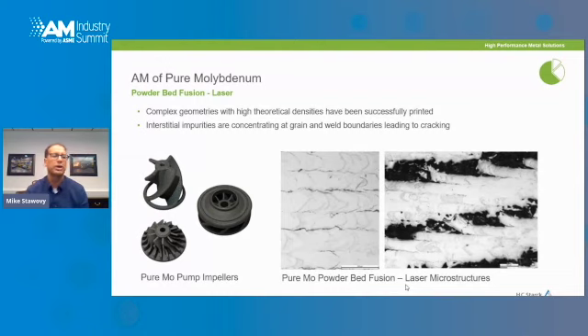Another example is powder bed laser fusion of pure molybdenum. These can also be produced in complex geometries, and we've been able to produce some pump impellers that you see on the bottom left made out of pure molybdenum. But there are interstitial concentrations that concentrate at the grain boundaries and the cell boundaries. And some of the microstructural photos you see on the bottom right show some cracking that occurs between the cell boundaries of this material. And in some cases, the stresses get so high that those cell boundaries can pull themselves apart just due to the stresses upon solidification. And that's the enlarged photo that's shown on the bottom right.